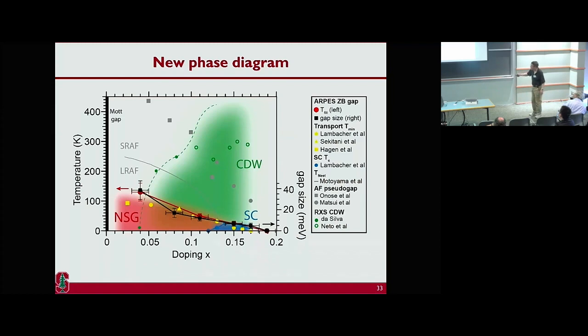So one way to think about it is you are fighting for the same piece of Fermi surface. At a higher temperature, you probably have some sort of charge density wave, and as you go down, this one seems to be smoothly connected into the superconducting gap. By exhausting, we have already used up antiferromagnetism, and it doesn't look like a charge density wave. What's left over, and given that it's so smoothly connected, it might as well be a superconducting gap.